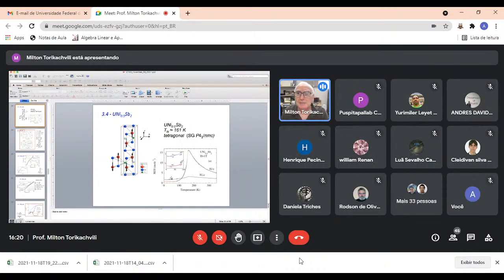And the last thing that I want to show is this one system, uranium nickel 0.5 antimony 2. Very interesting system. It orders antiferromagnetically at 161 Kelvin. This is the magnetic susceptibility versus temperature. There are these two very strong features here at 161 Kelvin. But if you blow up this image here, you'll see these two very small features that are sort of puzzling. They're centered near 40 and 80 Kelvin. And this is puzzling me to this day.